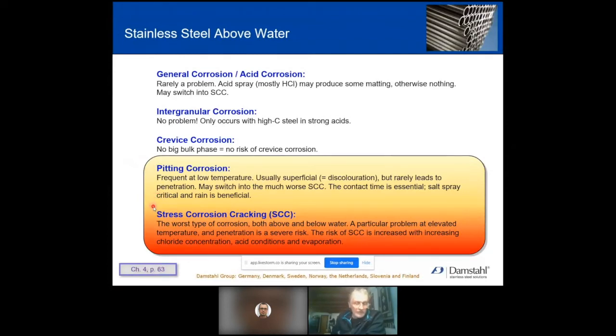If you have a higher temperature, and we don't talk like 400-500 degrees, it's just 100 degrees, there's a very good chance we're going to encounter stress corrosion cracking, and you don't want that.